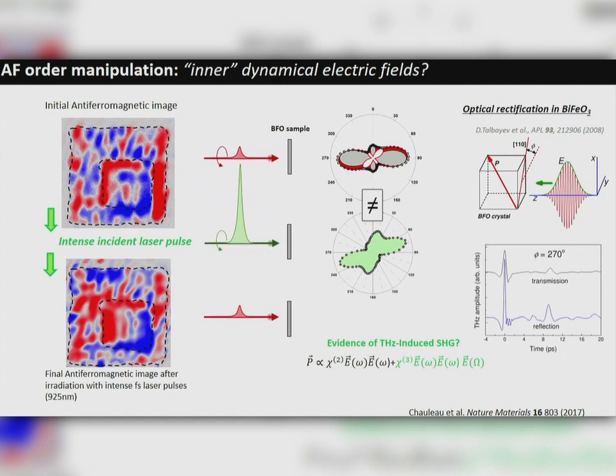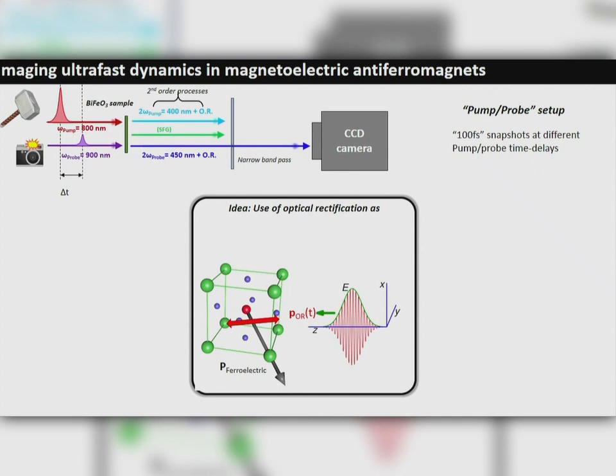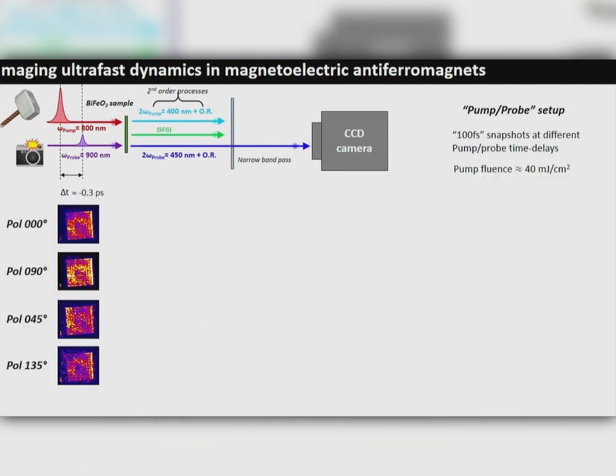And at that stage, we said we really need to dig into the dynamics, and so we moved to time-resolved second harmonic generation to try to investigate and image this contribution. So this is what we have done. Basically, the configuration is the following. We still have our probe, which is second harmonic generation at 900 nanometers. But then we bring a pump at 800 nanometers, with the idea that we want to use this transient polarization to trigger dynamics and see if we can do something with it. And this is what we've done.